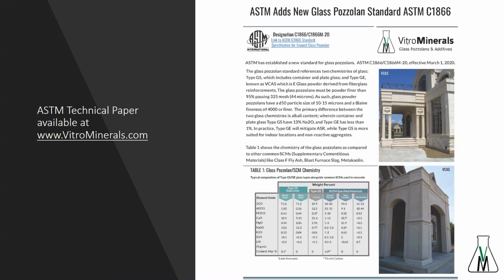The chloride ion permeability is improved, the sulfate resistance is improved, and all the properties that you would expect from a good pozzolan come to the fore when you use glass pozzolans. Of course, glass pozzolans have a lower quantity market availability than fly ash and slag. There's millions of tons of fly ash and slag available. Our plant down in Jackson, Tennessee is about a 20 to 30,000 ton per year plant. We have another plant in Indianapolis that's about 10,000 ton. And they built a new plant in New York, actually Connecticut, that's going to be about a 25 to 30,000 ton plant. These are not large plants, but they do take care of a municipal waste problem, and they do close the loop on everyday products that consumers use.